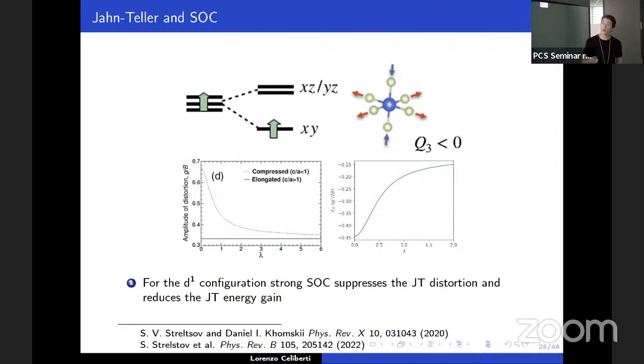Another interesting question is how this Jahn-Teller distortion interacts with spin-orbit coupling, because as we saw at the beginning, spin-orbit coupling is changing the shape of the orbitals. So it's also changing the charge distribution within the octahedron, especially in this case, for the Q3 distortion in a d1 Jahn-Teller impurity. These are results of exact diagonalization for an impurity model. They show that spin-orbit coupling quenches the Jahn-Teller distortion. On the plot on the right, you have the Jahn-Teller energy, which is the energy difference between the undistorted configuration and the distorted one. You see that this energy gain is basically decreased as you go to stronger spin-orbit coupling. So you have a competing interaction between these two, and this will also be interesting for polaron physics.